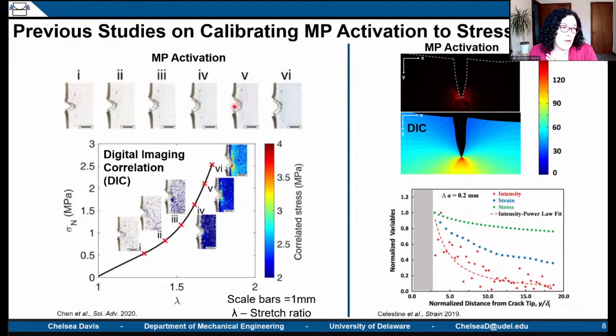So if you take something like a multiple network gel and you put a notch in it and then deform the material, as you deform it further and further, you get a larger stress field arising around the tip of that crack. And they correlated this to the activation or the intensity of their mechanophore. And this has happened in rubbery and glassy systems. But for us, we're working with polydimethylsiloxane. We're working with Dow Sylgard 184, sort of the classical perfect elastomer, which is a terrible way to describe it, but it has become a material that a lot of people in the soft matter mechanics of materials community use as sort of the test subject of choice.